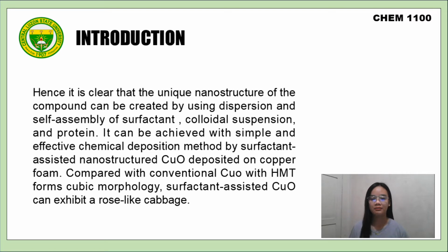The organic surfactant plays a vital role in the prepared material's structure and morphology. Hence, it is clear that the unique nanostructure of the compound can be created using dispersion and self-assembly of surfactant, colloidal suspension, and protein. It can be achieved with a simple and effective chemical deposition method by surfactant-assisted nanostructured CuO deposited on copper foam. Compared with conventional copper oxide with HMT, which forms cubic morphology, surfactant-assisted copper oxide can exhibit a cabbage rose-like structure.